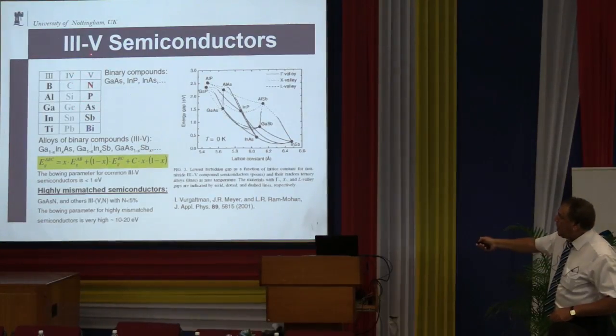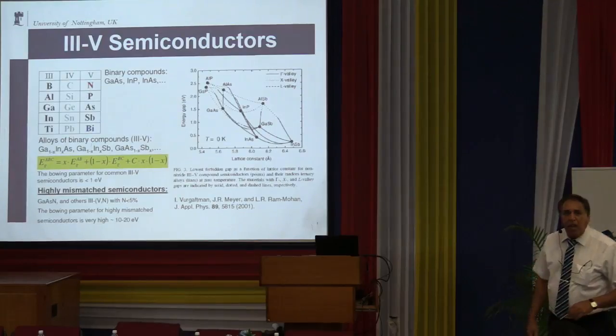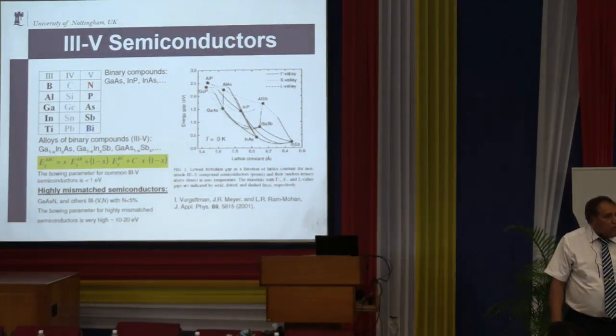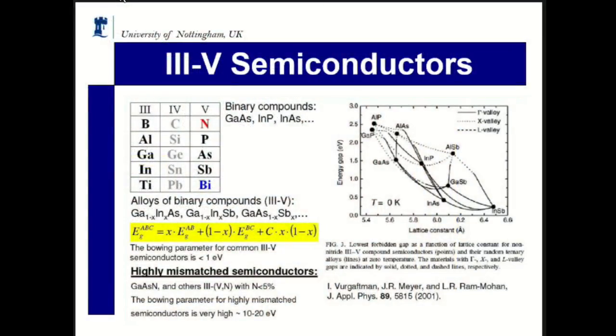Because the size of the atom goes this way. So by adding nitrogen to this material system, you replace some arsenic atoms by nitrogen, and you're going to decrease it. But you're replacing a bigger atom with a smaller atom, so you're going to have some problem in terms of properties of this material system. That's why it was very difficult to really make.